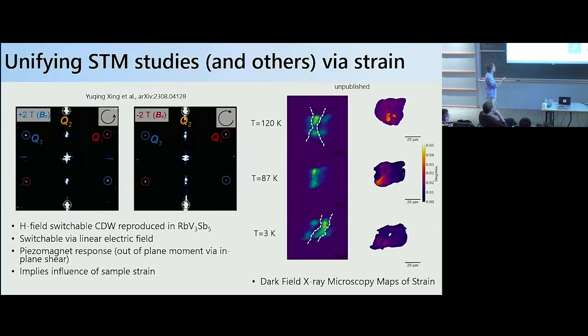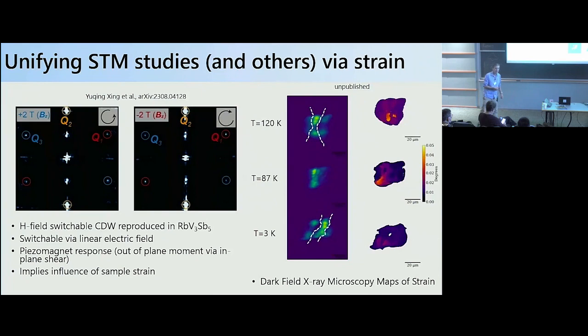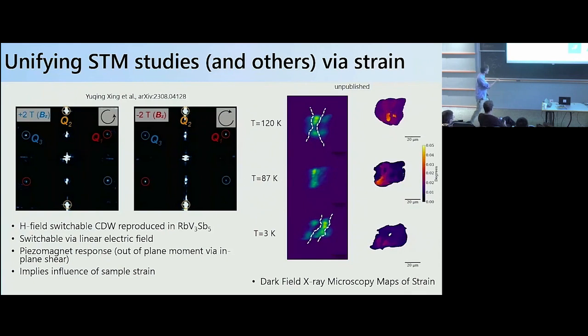This might explain discrepancies between optical experiments — why circular dichroism is seen but no polar Kerr effect. An audience member notes that circular dichroism cannot distinguish simple structural chirality, and only the Kerr effect can do so at the optical level. Using dark-field X-ray microscopy to look at strain texture, one can see that the sample illumination area is inhomogeneous, with regions of stronger strain that migrate around as you cool below the CDW. The hypothesis is that unintentional strain plays a large role in some experimental discrepancies, as these are very soft materials.